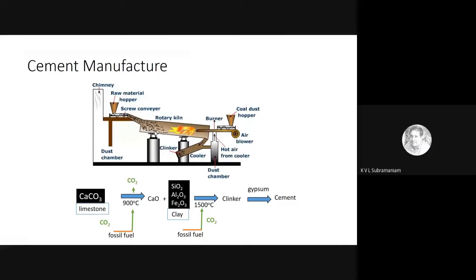Now, as I heat the two of them, the calcium oxide and the clay, the calcium fuses with the silica, and then I get the calcium silicate. And of course, because I also have alumina and iron, I also get the calcium aluminate and the calcium aluminoferrite phases. These are what we call our Bogue compounds that we read about in cement chemistry. And what comes out of this is what we call clinker, which is then ground with gypsum to produce cement.